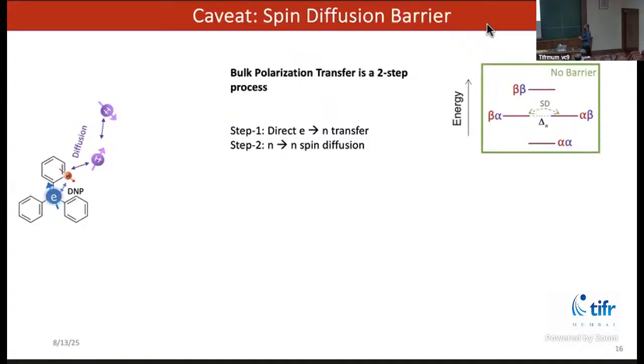So overall, what I have said so far is DNP involves two processes. There is a transfer from unpaired electron to the nearby nucleus, and then there is a spin diffusion from that nearby nucleus to the bulk nuclei. So there is a diffusion process and there is a direct DNP process. The caveat is, if you make one process efficient, the other process becomes inefficient. So if one would want to make the DNP transfer very efficient, the spin diffusion process becomes inefficient.